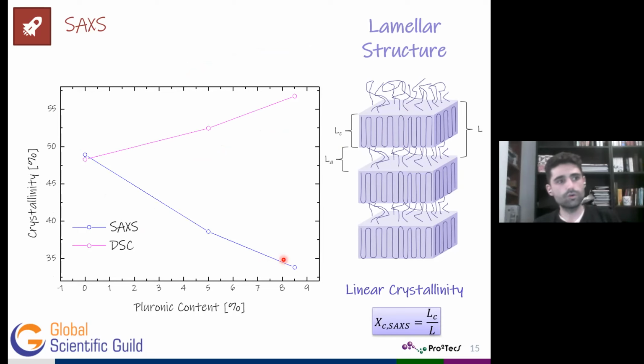From those results, we could also analyze the crystallinity, or better said, the linear crystallinity, according to this equation. But this crystallinity only considers those crystals with the lamellar structure or the lamellar arrangement. If we compare those values obtained from SAXS, that blue line, with those obtained from the DSC tests, we can see that in the case of pure PCL, there is a good agreement between the two techniques. We have almost the same crystallinity degree, denoting that all the crystal in PCL has the same lamellar conformation.